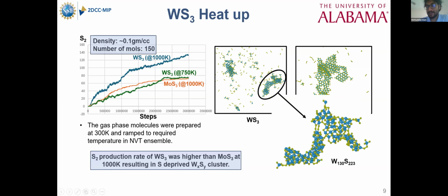Also, the cluster stoichiometry is almost 130 to 223, which is much less than a 1:2 ratio. So we came to one conclusion: tungsten and sulfur may be more prone to a 1:1 ratio according to our ReaxFF, which needs to be corrected.